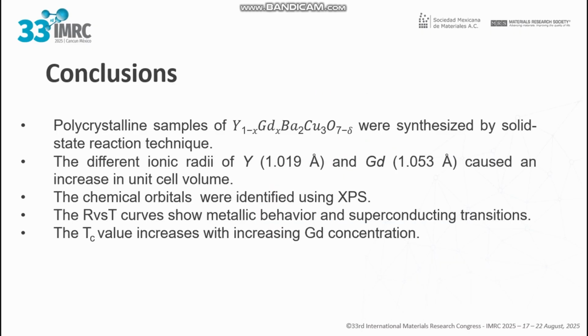So to sum up, polycrystalline samples of yttrium barium copper oxide doped with gadolinium were synthesized successfully by the solid state reaction technique. We also think that the different ionic radii of yttrium and gadolinium were the cause of the increase in the unit cell volume of the compounds found with Rietveld refinement. Later, we saw that the chemical orbitals were identified successfully using XPS. And lastly, the R versus T curves showed the metallic behavior as well as the superconducting transitions, wherein the Tc values were found to increase with the concentration of gadolinium.